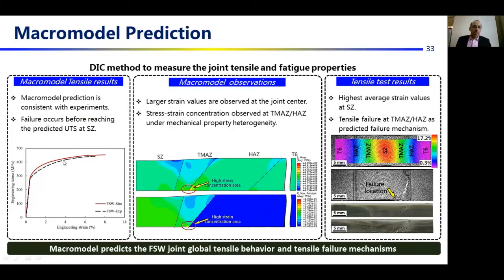Macro model predictions also show results consistent with the experiments, and the failure you can see occurs before the predicted UTS at SZ locations, and larger strain values are observed at the welding joint center because of its lower yield strength, and we can see the stress-strain concentration at the TMAZ-HAZ border because of the mechanical property heterogeneity. And the tensile failure results from the experiment show higher average strain values at SZ, but the failure occurs at the predicted stress-strain concentration area, which validates the macro-model results. And tensile failure happens at this location.